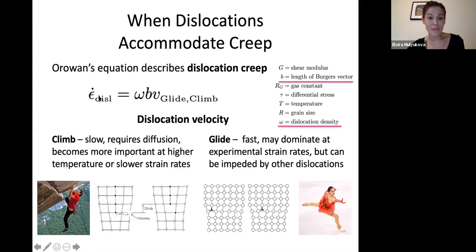Okay, so the strain rate by dislocations is proportional to dislocation density, so just how many of these dislocations you have to move your strain around. The length of the Burgers vector is just characteristic of a dislocation of a certain type. And then the velocity at which these dislocations move. And dislocations can move by different processes. So here in detail, I'm showing climb and glide.